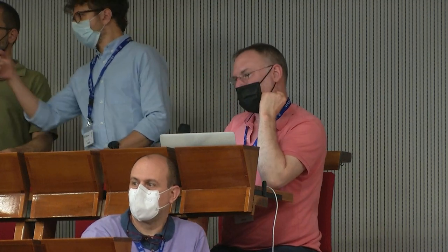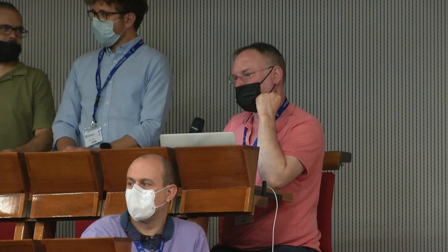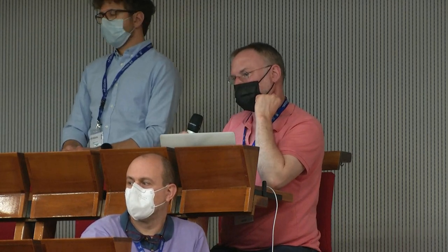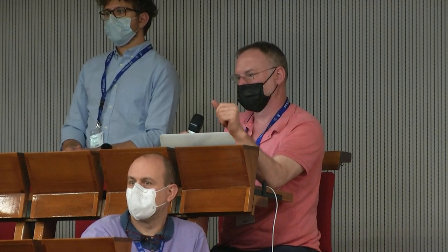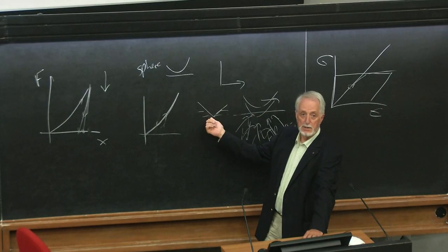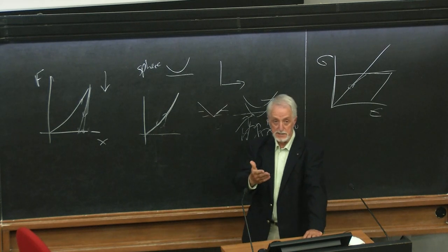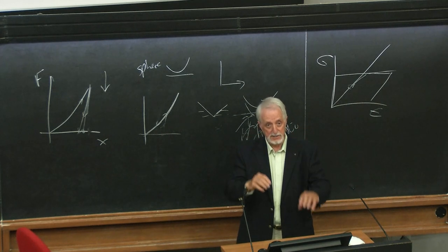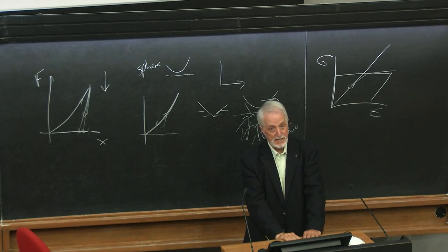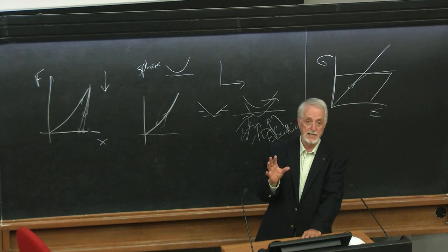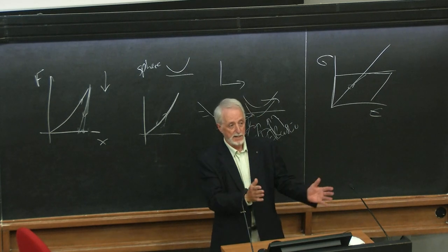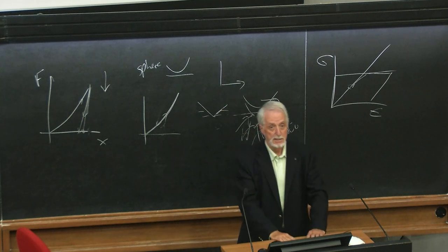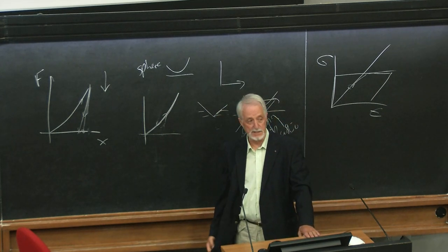Also, more importantly, as we realized recently, it's strain rate that matters for those. And of course, that was the point originally, that the interface region is not typical of the bulk. And that's another reason we described earlier on. I think it's broadly true that the sharpest of these tips will just about explore that region. But the problem is, as we've discovered in recent times, it isn't just the so-called yield strength change due to dislocation interaction. The strain rate matters a great deal at that point. And I think this is one of the things we should take into account when we're thinking about simulations. The fact that there's a time scale difference between what's happening in the experiments and the simulations is still pretty serious. There's a very strong strain rate effect in all of these things, especially in metal.